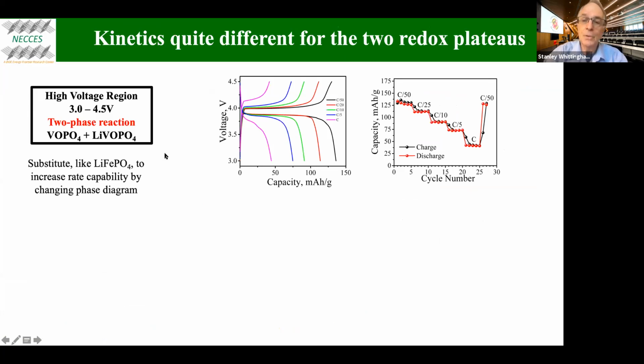The kinetics in the two voltage plateaus are quite different. So let's look at the high voltage region first. This one is at about 4 volts. Here's C over 50, so this is a very slow rate discharge. So it's 50 hours. Here is 1 hour, and you can see we're losing capacity very fast. So this is slow kinetics, and we show the capacity as a function of the rate in here. What we've determined in this particular material is a two-phase reaction. So we've got vanadium phosphate in equilibrium with lithium vanadium phosphate. So we have to nucleate this new phase, and we're hoping to turn this into a single phase reaction. But at the moment, this rate limiting step is limiting the material.